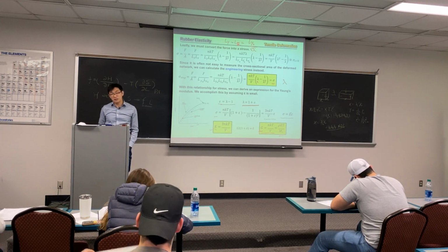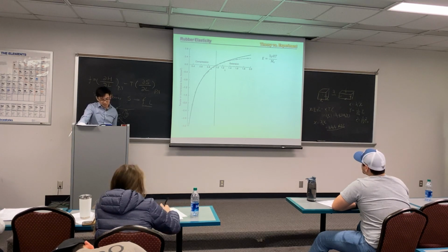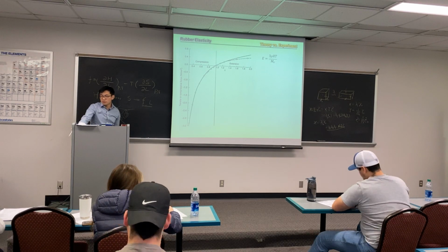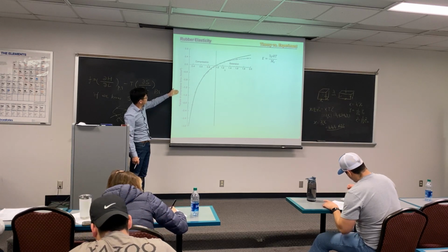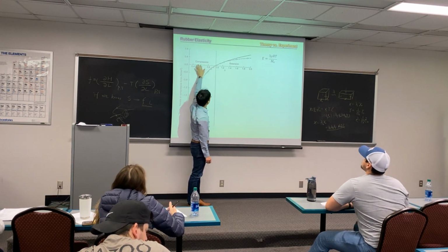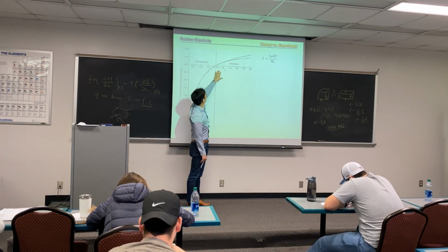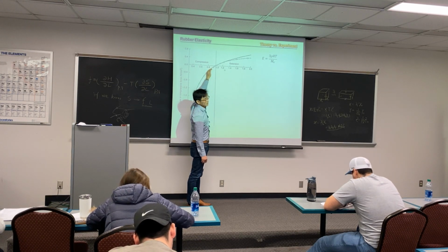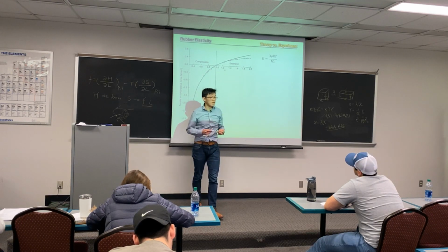This theory is actually very successful. As the last slide will tell you, this is what has been predicted and measured in the real world for rubber material. What we plot is the tensile or compression force. One is where it initially started off. This is compression, this is the extension, as we see the length. The solid curve is what is predicted by the theory we have discussed. The dotted lines are what was measured in real time.